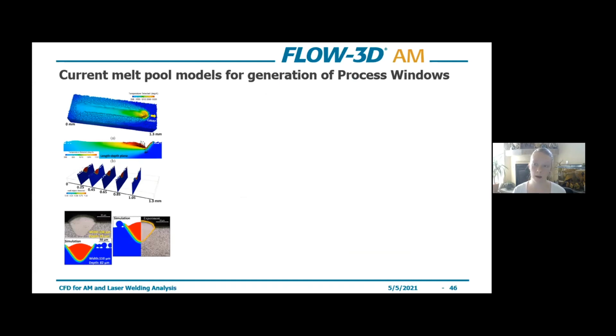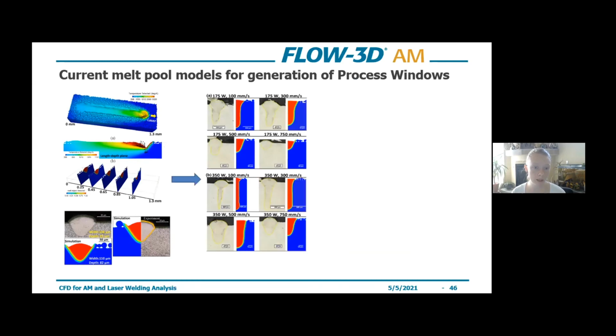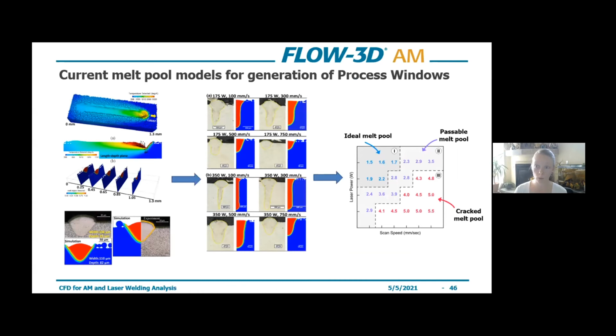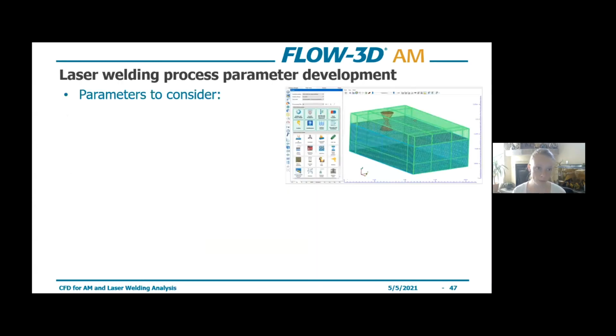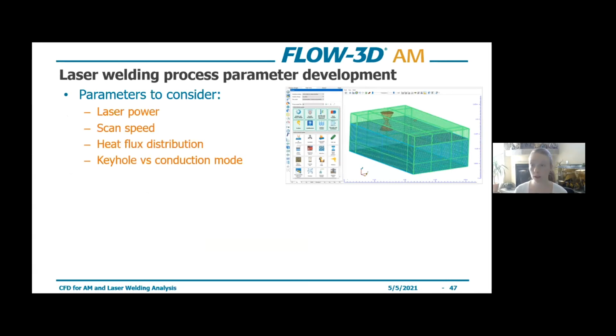So using melt pool models to do this, as you've probably inferred so far, we start off by doing a validation, compare with experiments, make sure everything looks good. Then you can do simulations of different process parameter combinations. Ultimately, we're trying to develop that process parameter window to identify those parameters that will lead to conditions which are favorable and which will lead to conditions which are unfavorable, and we should probably not use those parameters. So there's lots to consider here. Laser power, scan speed, heat flux distribution, whether you want to be in keyhole mode, conduction mode, what kind of atmospheric conditions you have, what are your material properties that you're working with.